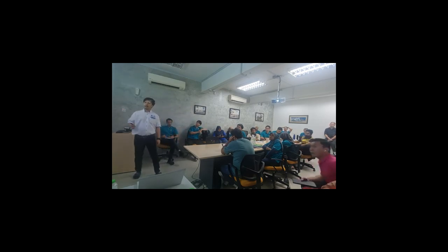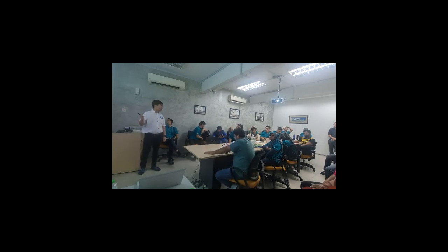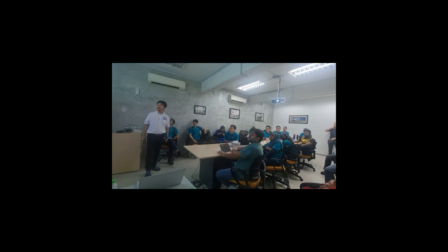This is what I mean. Let's say you look at one of the actual results. One, you improve the slump: for the original mix, you add in just admixtures, from 100 to 150. The second consideration, from 0.55 reduced to 0.5, you get a higher strength. Third one, you cut down the cement cost, cement saving with the same slump or workability.